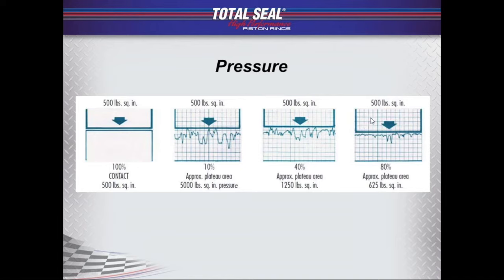So to the right slide here, we're looking at what we're looking for in a properly plateaued cylinder. We want about 80% plateau, so about 80% of the surface flattened out. You look at the pressure numbers, we're down to about 625 pounds per square inch. Very few peaks, a lot of plateau, nice valleys.